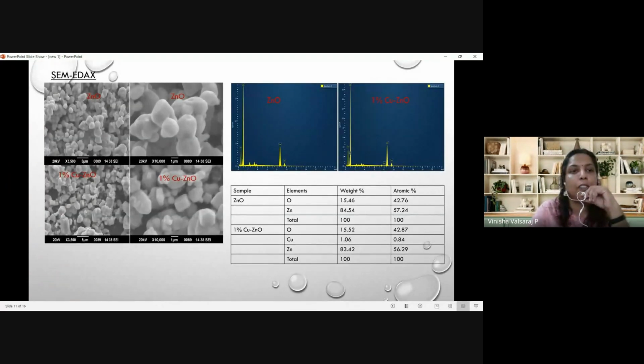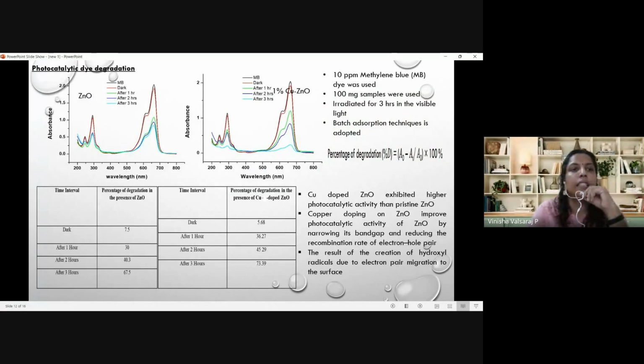This is the morphological study. We did SEM and EDAX, and EDAX also confirmed the 1 weight percent doping in the ZnO. To determine the photocatalytic ability of this material, we did a dye degradation study using 10 ppm methylene blue solution. The batch adsorption technique was adopted for this study, and it was irradiated for 3 hours in visible light. At different time intervals, we collected the methylene blue and recorded the absorption spectra.